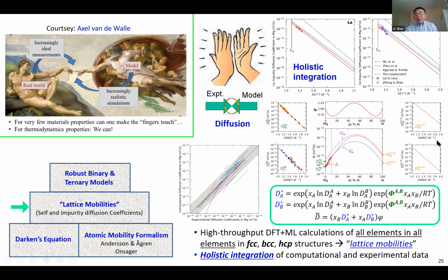Because as I mentioned in the past, if you have very little data, because the solubility is only this much, that's the only thing you can measure, and you are trying to fit so many parameters, and this is unknown on the aluminum side, and you use a very small data set to fit a large number of parameters, it's not going to give us very reliable mobility data. I think the holistic integration of computed and experimental data really will be able to help. I think the community is ready to establish this lattice mobility. So this is a really important stepping stone in our quest to get an all-encompassing, reliable database for all the solutions.